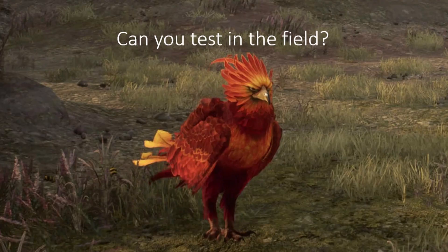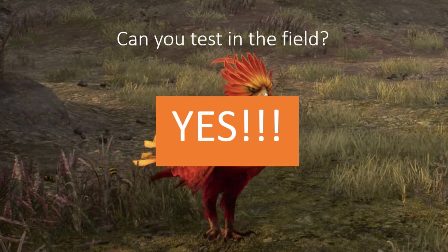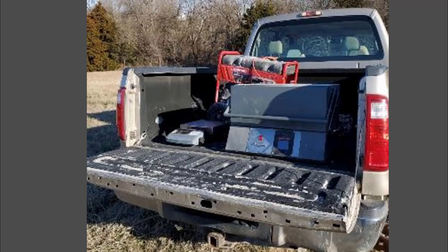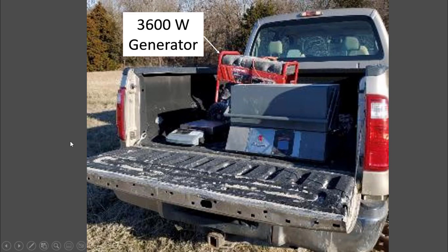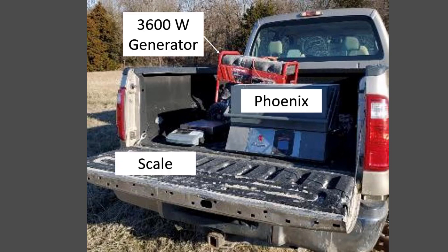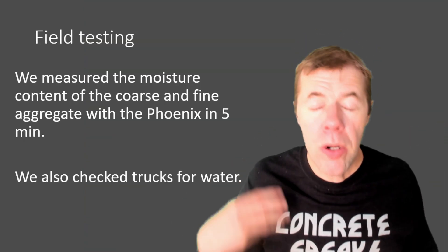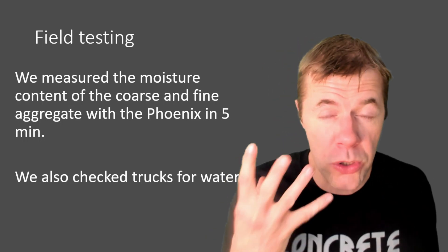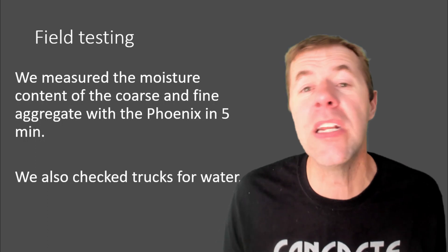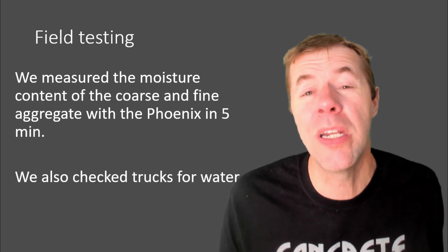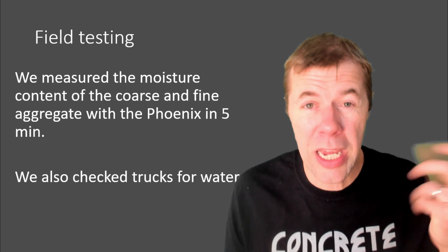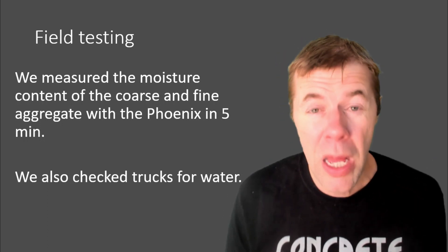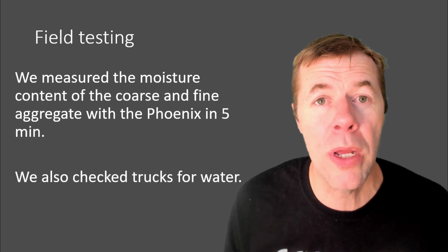But can you test the Phoenix in the field if you wanted to? Sure you can. Yeah, no problem. Here is where we did it. We put it in the back of a pickup truck. We used a generator to run the Phoenix. That is the Phoenix oven itself. There is the scale that we used to do everything with. We did everything the same. But what we did is we first started out, we went to a ready-mix plant. We measured the moisture content of the rock and the sand with the Phoenix. We did the cook-offs in about five minutes. Then we actually used a camera to check the trucks for how much water was inside of them. And then we actually went and made concrete.